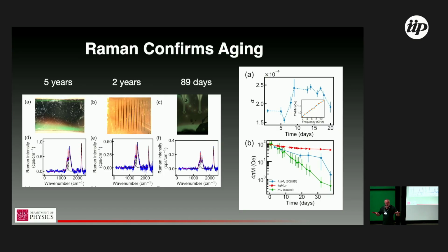So there's something happening with a structural relaxation over long time at high temperature, presumably this is sort of annealing. Like, remembering room temperature is quite hot for this material system, right? It deposits at only 60 C. So, again, if you're a pessimist, one boundary condition, don't use this material for building sensors that you're going to put next to a jet engine. But more optimistically for the science, it suggests that if this really is a class of materials, there's likely changes we can make to address this relaxation and perhaps get more long-lived magnetism. That being said, it's still pretty long-lived.